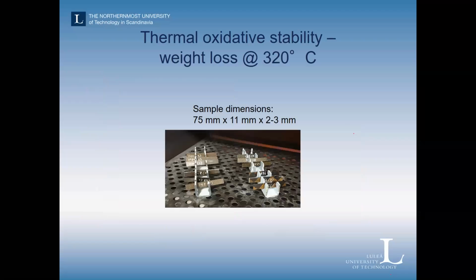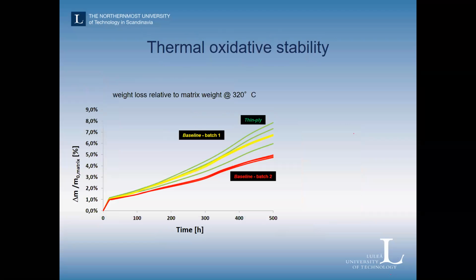Let me see. Okay, now it's responded. It took a while. So we do thermal oxidative stability test by measuring the weight loss, again at 320 degrees over time. So these are the type of samples we place in the oven and measure then the weight loss over time. And we obtain results like this, where we have the weight loss in percentage of mass loss versus the matrix weight that we have over time.